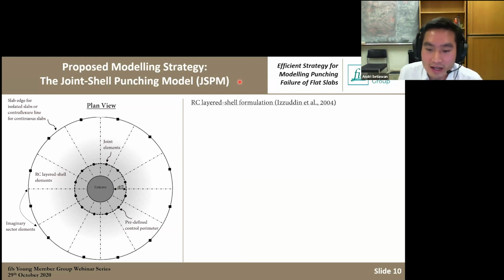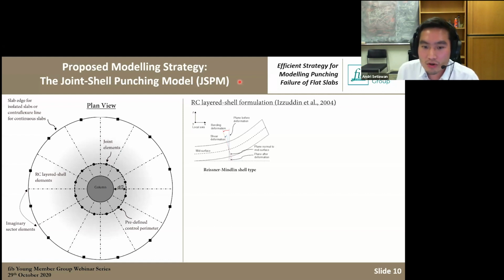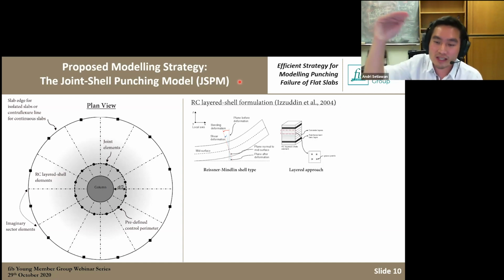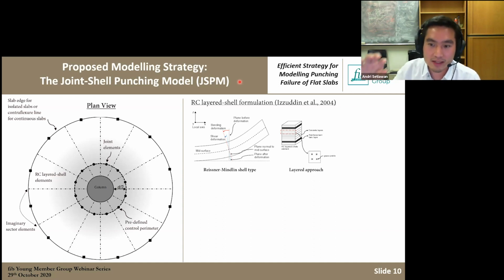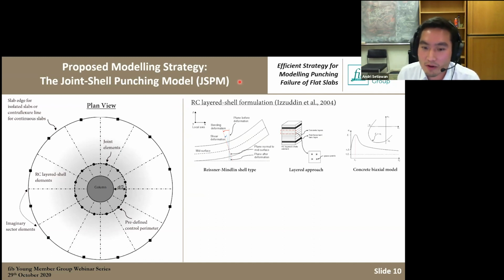So for example, in this work, I'm using the shell formulation proposed by Izzuddin et al. We are using the Reissner-Mindlin shell type, where plane sections remain plane after deformation, but not necessarily normal to the mid-surface of the slab. We consider the shear deformation. And we are using the layered approach, where we discretize the shell into several layers through the thickness. We model the reinforcement with a smeared approach, as a layer with an equivalent thickness, basically. And we also have a concrete biaxial model to consider the interaction of compressive, tensile and shear stresses in the in-plane direction.